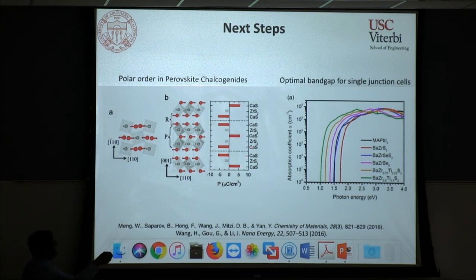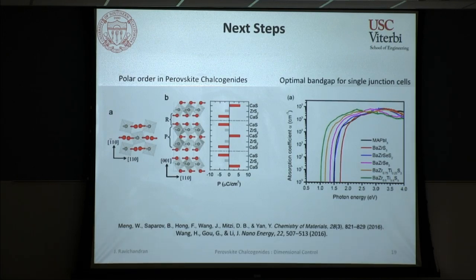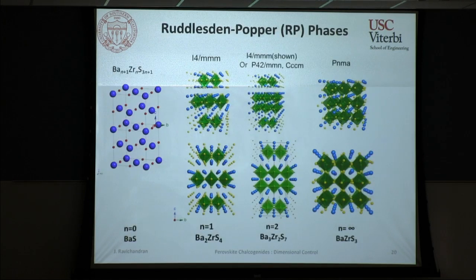There was a prediction that barium 3 zirconium 2 sulfur 7, the Ruddlesden-Popper layered structure, could show this effect. So we wanted to first start off with the barium zirconium sulfur series, which we have already started making. So what we wanted to do is to take these materials and try to make these natural superlattices by inserting an AX layer in between the perovskite blocks and see how that affects the optical gap and their polar order.